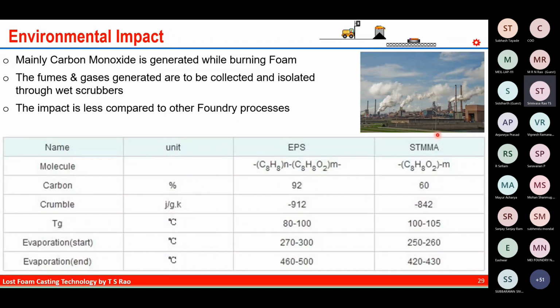Then if you see the environmental effect of the process, EPS contains about 92% carbon and STMMA contains about 60% carbon. Because of this, when you pour hot metal into the foam molds, the carbon monoxide which is generated, we need to collect it carefully. We need to collect the fumes and we need to isolate them while passing through the wet scrubbers. If you see, the overall impact on the environment is less compared to any other foundry process.